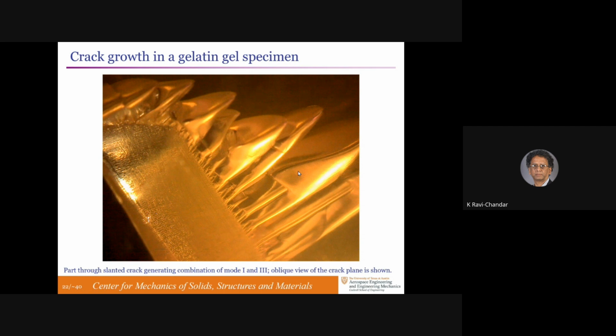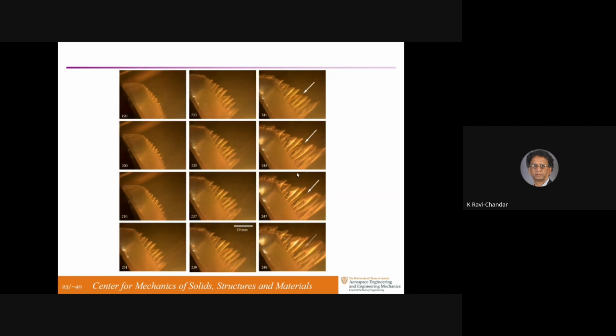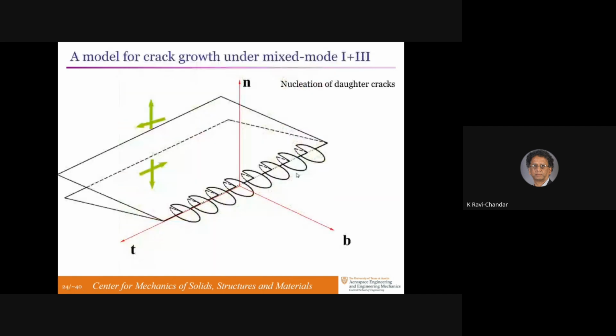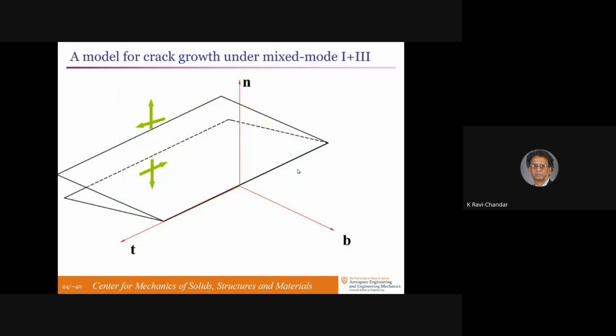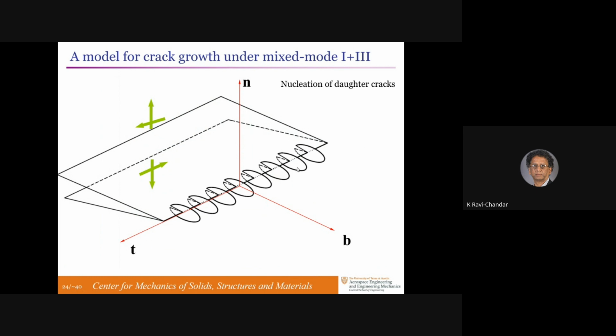And eventually, something connects them up from the back. And you're not able to see that here, so I have to show you a cartoon of what I think is going on here. So that's the parent crack. It spawns daughter cracks. The daughter cracks grow. They shield, and some of them grow more than the others. But now what happens is you're still subjecting them to this load, but the parent cracks will experience a larger mode 1 loading because